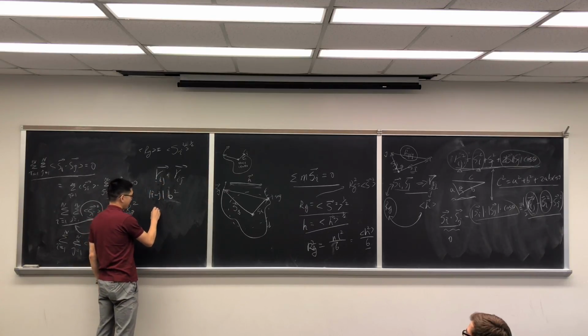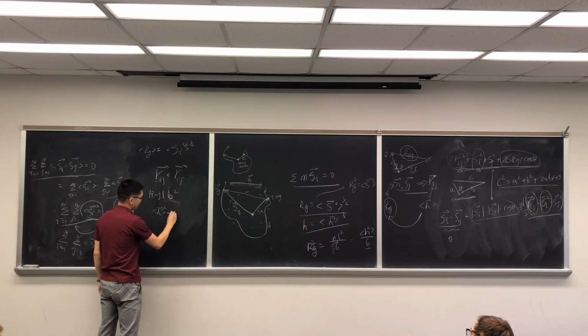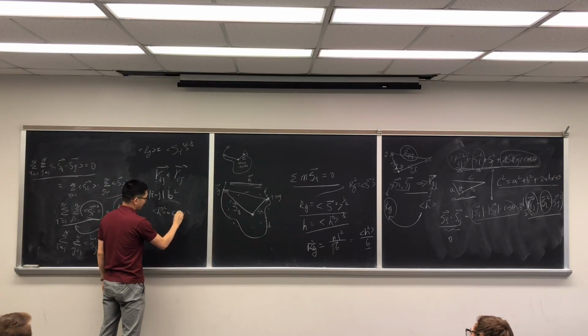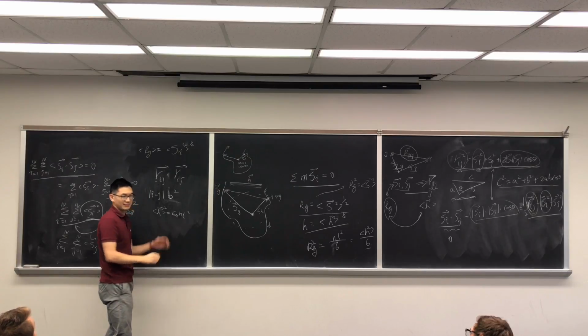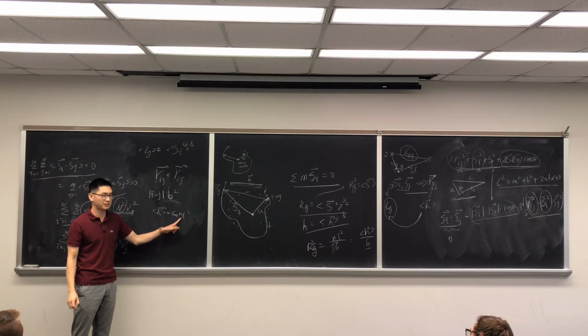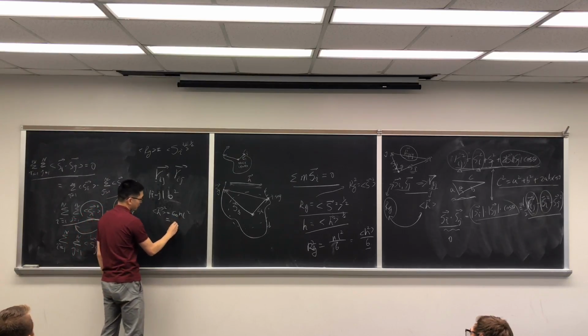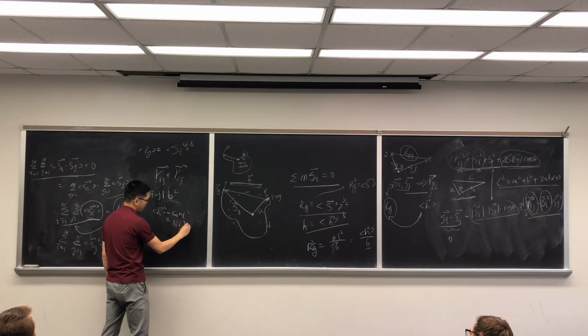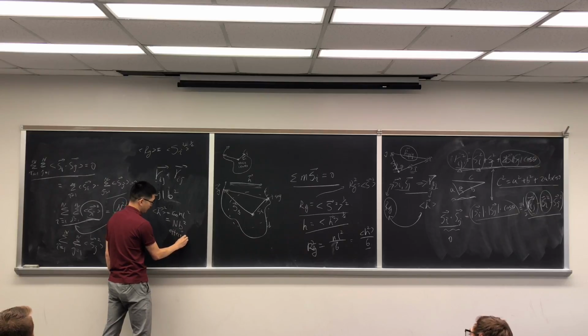So we talk about h squared equals C infinity n L squared. This is the characteristic ratio, number of bonds, and L. Or this will equal n b squared. This we call the effective freely jointed chain model, right?